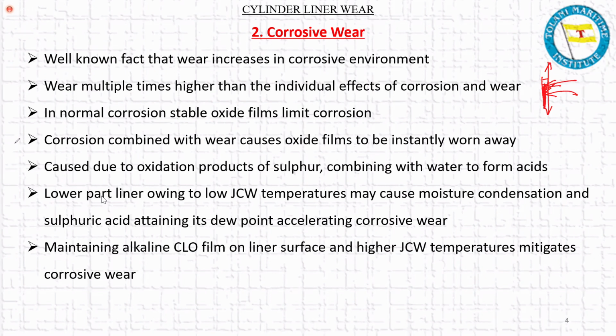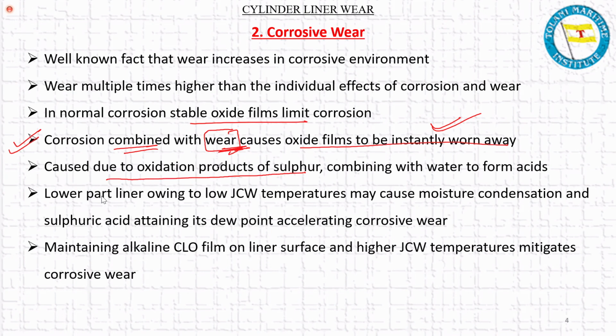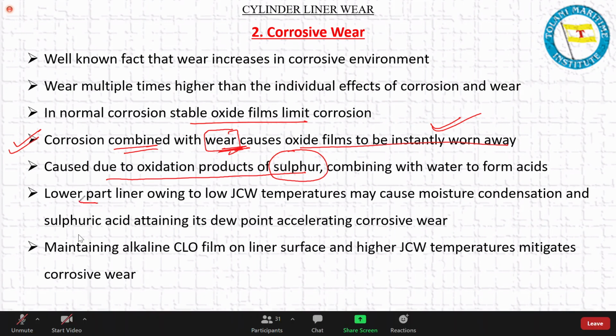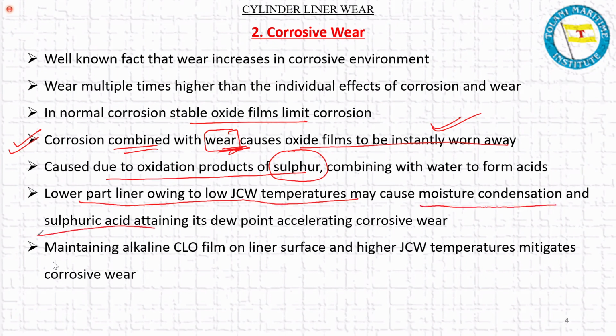Can you hear me? Yes, sir. So corrosion combined with wear causes oxide films to be instantly worn away. Corrosion causes the oxide film, but then frictional wear takes place. It causes this oxide film to go away immediately. Again, it is caused due to oxidation products of sulfur. We know that corrosion is taking place because of the sulfur content of the fuel. And there have to be some other conducive conditions which will cause the acid formation. Lower parts of the liners, owing to low jacket cooling water temperature, may cause moisture condensation and sulfuric acid attaining its dew point, accelerating the corrosive wear.